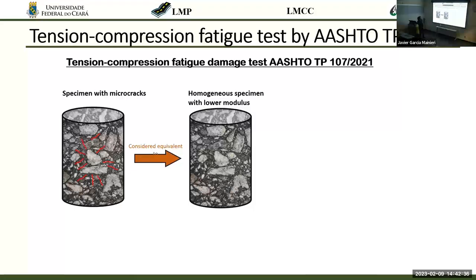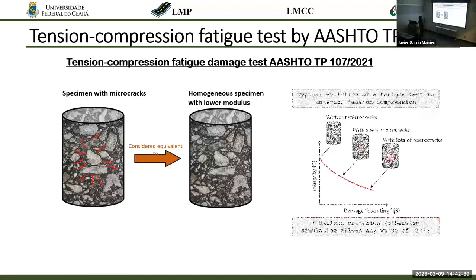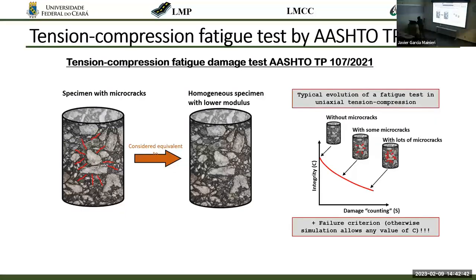And we do fatigue damage using VECD if you want. So I'll not get into the details. All of you probably saw that. It's kind of trying to count damage with some equation. It's a law for damage that's exposed. So there are many assumptions that may not be true, but it's a model as any other. And we try to have a unique curve between the damage or the integrity, which is one minus the damage from the mechanics perspective, with respect to this damage counting, which is also called a damage state variable in the literature. I do not like that name. I prefer to refer to it as counting. And this way, everyone knows that this is not actually completely mechanistic.